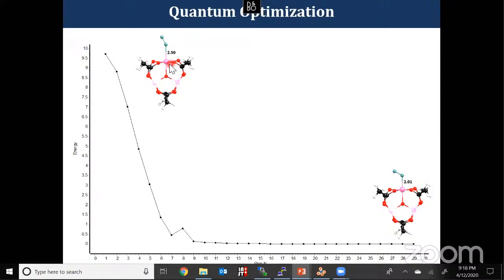For example, if it's interacting with a gas molecule, and the initial bond distance between the metal center and the first atom is 2.50 angstrom, you just forget about the bond. So there is no bond between the metal and the gas molecule initially. When I submit the input in the appropriate software, the initial energy will reduce, and after the 29th or around 30th step, I get this optimized structure.